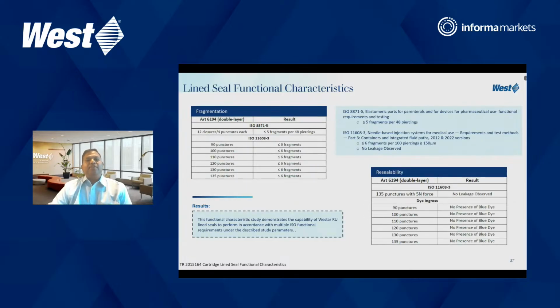So this is the actual data of fragmentation. On the left side, you can see as per ISO 8871, 12 closures were chosen with 4 punctures each. The results were less than 5 fragments per 48 piercing. When we have this data with different punctures, like a range from 90 punctures to 135 punctures, as per the ISO 11608, again the results are well within the limit, that is less than 6 fragments in all the cases, right from 90 punctures to 135 punctures.